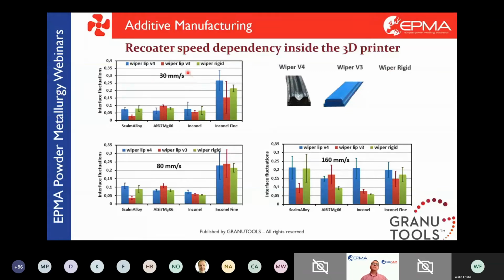So we have 3 graphs: one at 30 mm per second, one at 80 mm per second, and one at 160 mm per second. We can see that at 30 mm per second, the interface fluctuation for the 3 wipers are always in the same range. For the Inconel fine it's approximately the same range - we have big error bars here because it's fine. For Inconel it's the same range, for aluminum alloy it's, let's say, the same range. For the Scalmalloy we have a little bit of a bigger difference - we can see the single lip wiper is working better, but it's still approximately the same range.